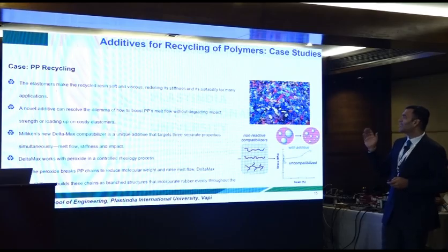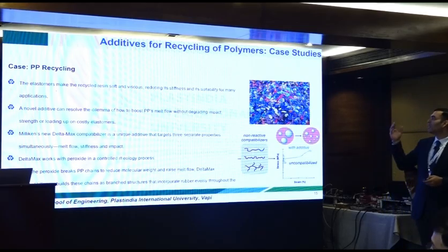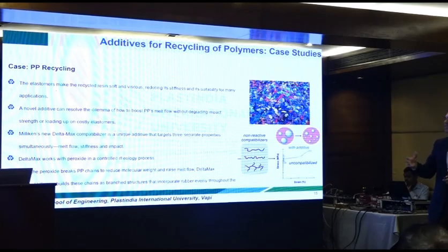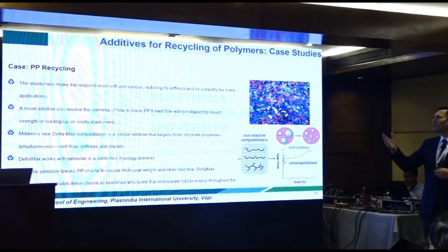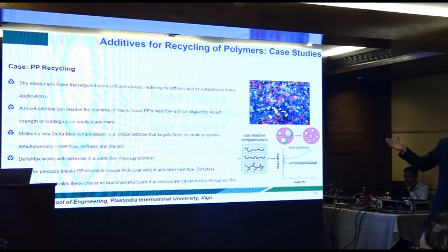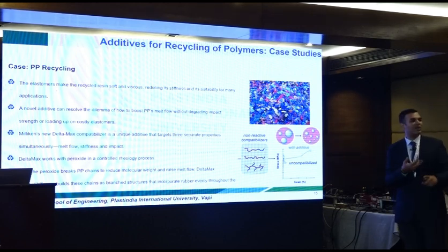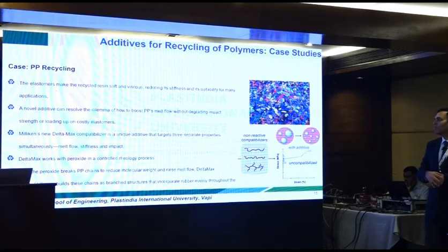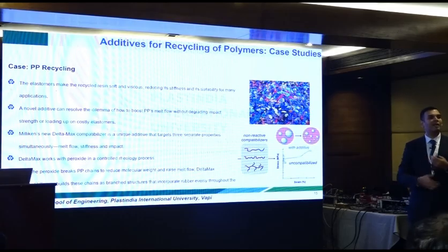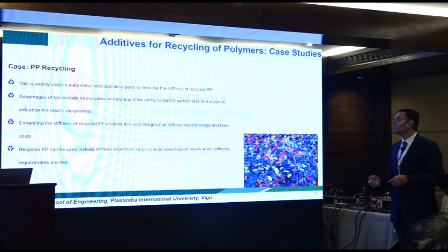The elastomers make the recycled resin soft and viscous, reducing its stiffness and the suitability for many applications. There are other materials which are there as well. Milliken is there, from Milliken's Deltamax, one of the compatibilizers is there. So Deltamax compatibilizer is a unique additive that targets 3 separate properties simultaneously, that is MFI, stiffness and impact properties. It works with the peroxide in a controlled rheology process, and after the peroxide breaks the PP chains and reduces the molecular weight and raises the melt flow, ये compatibilizer वो chains को पकड़ता है and it helps in increasing the strength properties that we talked about, impact strength or these properties.